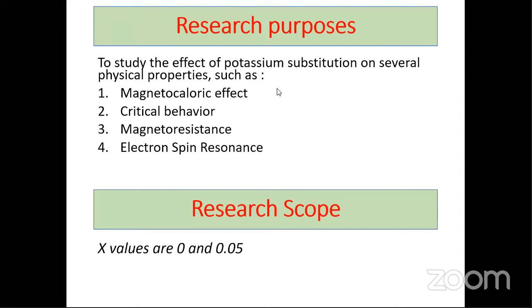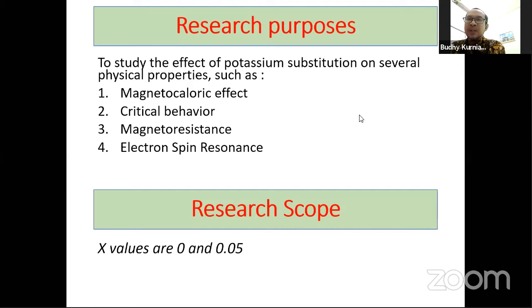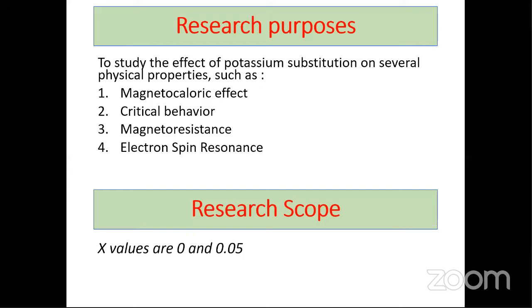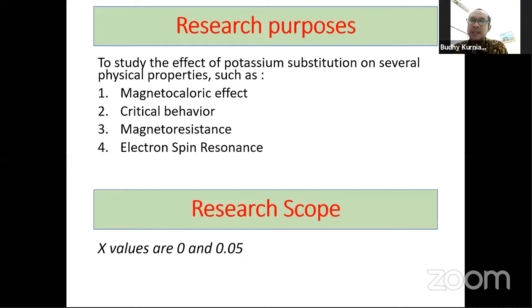And our research purpose in this system is to explore the magnetocaloric effect, and the base of the magnetocaloric effect is the critical behavior. What is the critical behavior? The critical behavior is the exploration above, at, and below the critical temperature or Curie temperature. And also we make magnetoresistance measurements and also electron spin resonance. And we limit our research scope to samples without and with potassium doping, with 0 and 0.05 potassium content. Next, please.